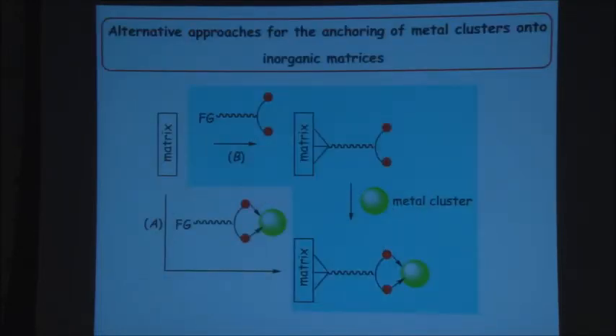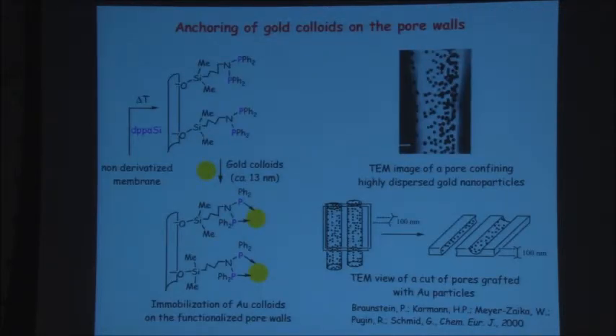Alternatively, you can have the second approach where you first functionalize the matrix with the diphosphine groups, for example, waiting here for the cluster to come in, and then it will accumulate to the cluster and form the desired hybrid material. So we took here these porous alumina membranes, which have a honeycomb structure that you've probably seen before, with pore diameters between 7 and 250 nanometers. This is an AFM view of the top. You see basically a bunch of cannellonis. And the idea is to put something specifically into the cannellonis in an anchoring procedure. So we took this approach here.